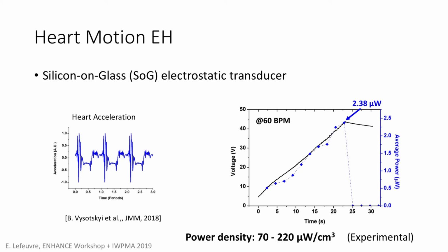So first we initiate the system with a very small voltage, a few volts, and you have the voltage across the storage capacitor as a function of time. And after 25 seconds, we reach a maximum of the voltage, and then the system is stopped due to the electrostatic force, which is too strong and stops the motion of the system. It's a non-linear effect, so the shape is not progressive.